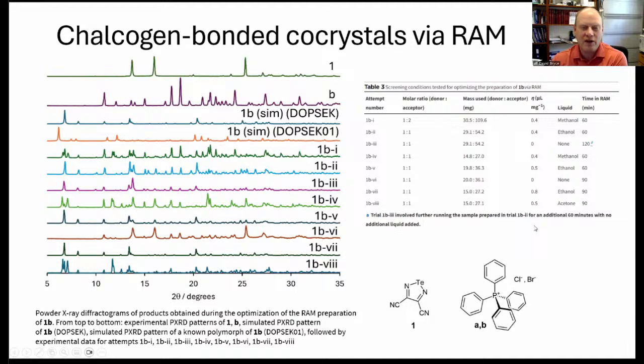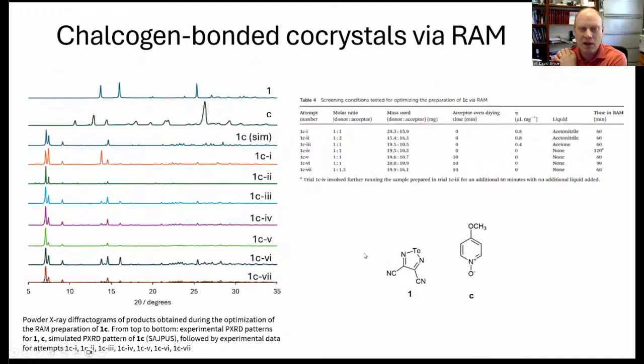Same thing with another molecule here. There are 2 known polymorphs of the cocrystal 1B by varying conditions. So different solvents, different amounts of liquid added, different molar ratios, etc. In no case do we get this second polymorph. But by adjusting the conditions, we can get the first polymorph, perhaps best in trace 1B5 here. Okay, again, just by adjusting conditions, you can see it's quite sensitive exactly to what we put in.